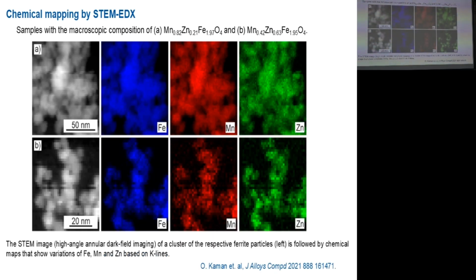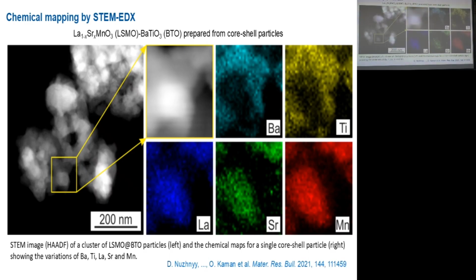Chemical mapping. I mentioned that you can include energy dispersive X-ray fluorescence analysis in your microscopy. It's very well available nowadays, and you can analyze chemical composition on whole maps of the sample, and you can prove, for example, that it is really chemically homogeneous, that some dopant is distributed in the whole sample. This technique is also very useful when studying some core shell particles composed of different compounds or different phases.